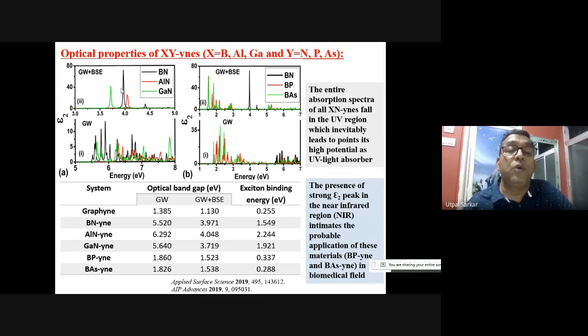So this is basically boron nitride here. Here you see that all these XY-ynes fall in the UV region, and that means this can be used as a potential UV absorber. And the presence of a strong epsilon 2 peak near the infrared region indicates the probable applications of boron phosphide. This is boron phosphide you see here. So there is probable application of this boron phosphide and boron arsenide in biomedical applications.